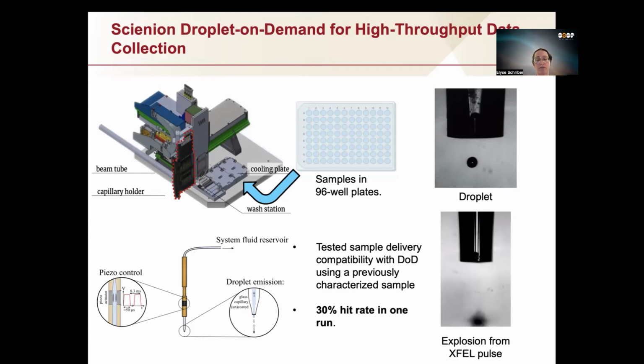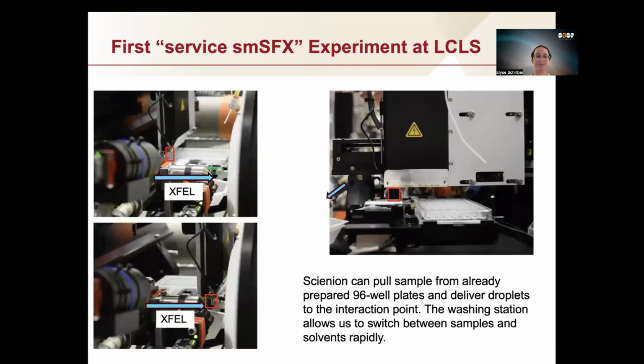We tested this method for small molecule crystallography using a previously characterized sample, and we found that the hit rate went up to 30% in one run. Usually it takes us several go-arounds with liquid jet sample delivery to attain that. So to immediately be able to get a 30% hit rate was really exciting for us. It made us think that it was possible to actually do high throughput data collection with small molecule SFX. And this is just an example of the droplet itself, and then the explosion from the XFEL pulse. So we can synchronize each pulse to the droplet, which is also exciting because it means we're using less sample and we're also producing less waste.